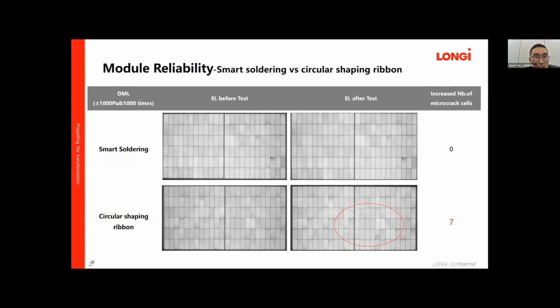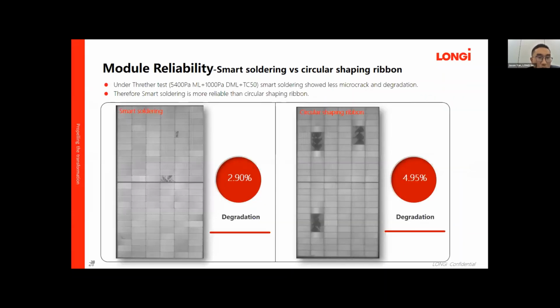And we also did the dynamic and mechanical loading test for these 2 different technologies. For the smart soldering, we can see EL after test showed no micro crack of cells. However, for the circular shaping ribbon, we can find the micro crack of cell increase about 7 numbers. And we also did another threshold test, the test condition is about 5,400 Pascal mechanical loading plus 1,000 Pascal dynamic and mechanical loading and TC 50 cycles.